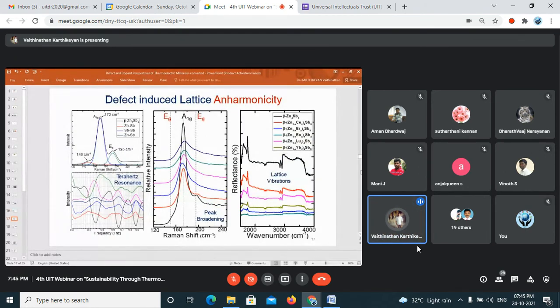And this is the additional characterization we did to prove that phonons are being filtered. We used terahertz spectroscopy, which is more advanced than FTIR spectroscopy, where we shine the terahertz radiation on the sample and get the vibrational data from the sample, which shows the harmonicity. The black one here shows the harmonic oscillation of the lattice for the undoped phase. Whereas for the red, blue, pink, and the green, you see it's not in an orderly manner, it's totally distorted, which means that the vibration pattern is totally disturbed by the dopant effect and creates anomaly.